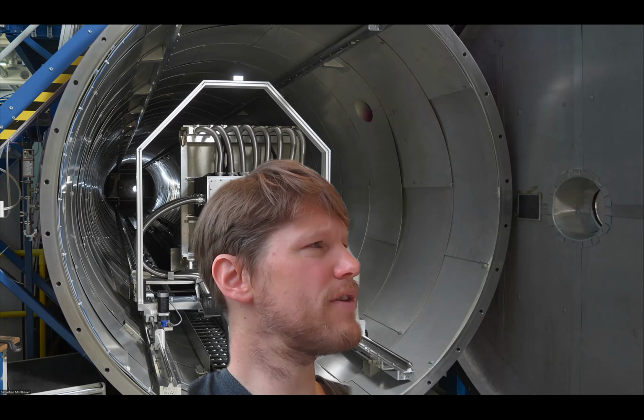That's what I tried to extend a little bit in my thesis. It was not only visualizing the vortex lattices, but also extracting the form factor using this Bayesian analysis. I was more talking about that the Bayesian analysis exploits the fact that this is a crystal lattice. So if I have a peak here, I need to have a peak here just due to symmetry reasons. Would that be a good idea to do that? Just with one single peak.